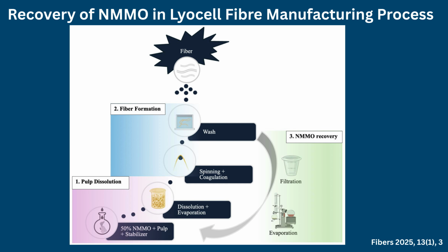The cellulose solution is extruded into water, where cellulose regenerates through solvent exchange rather than chemical decomposition. A defining advantage of the Lyocell process is its closed-loop solvent recovery system, in which more than 99% of NMMO is recovered and recycled. Consequently, Lyocell production generates substantially lower emissions than the viscose process.